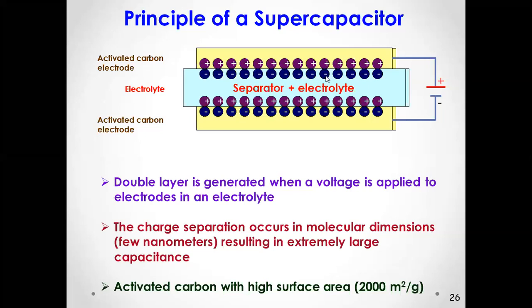So that's why nanomaterials play a major role, since they have a high surface area. If I can increase the surface area more and more, I can also separate charges more and more. So this obviously will help us to increase the energy density of the system. In most systems only carbon materials are used, activated carbon materials, since everybody knows the surface area of this carbon can be increased to even more than 2000 square meters per gram. In addition to the surface area, since we are using this as an electrode, this material should have minimum conductivity. Conductivity need not be as high as metal. Okay. So here we need some minimum conductivity.